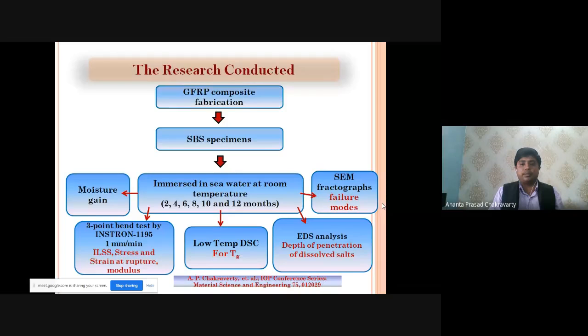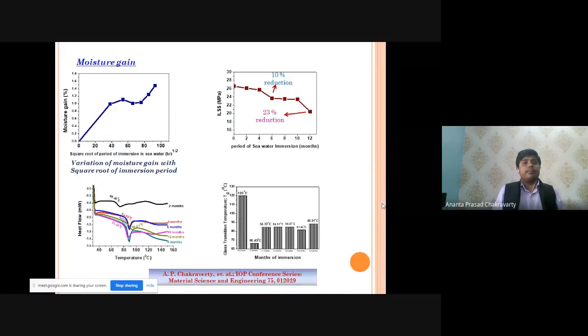and its microstructural properties. So you can see the moisture gain improving, and at a certain level of days it becomes constant, after which it improves again. That means I have to use the material within these durations. Beyond these durations I cannot use it. Okay, that is a very small material I have fabricated. But if I increase its dimensions and its layers, then its sustainability capacity will increase, maybe up to 5 years or 6 years or maybe up to 10 years.